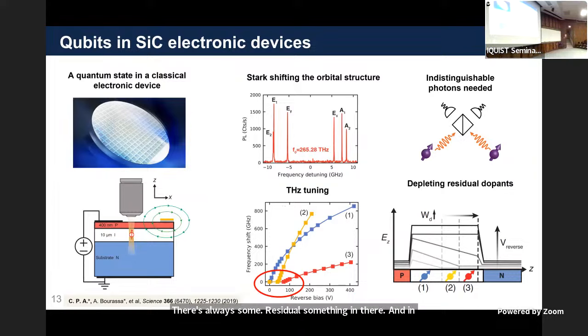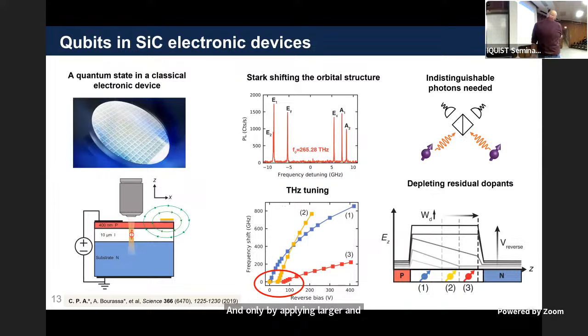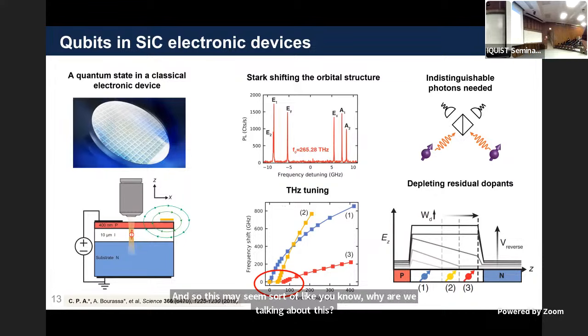So if you think about a PN diode, you put a P-type semiconductor and an N-type semiconductor next to each other, there's a little depletion region, a little electric field at that interface. And in this system, because this is slightly N-type, that depletion region and that electric field first only drops across this P to slightly-N interface. Only by applying larger and larger reverse biases do you grow this depletion region and make an electric field that looks more uniform through this intrinsic layer. And so this may seem like, why are we talking about this? This seems useless. But this actually becomes really important in the next slide.